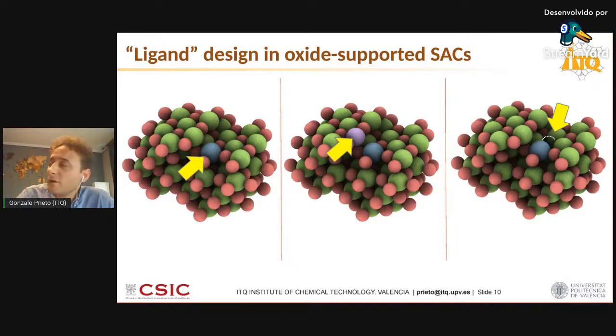Second degree of design relates to the oxide support itself, where we can isomorphically substitute those cations which are intrinsic to the oxide support by different ones. And this way, we are introducing Lewis acid centers close to our atomically dispersed metal with different acid strengths. That's what I represented by substituting one of the green atoms by this purple atom there. Those are cations, and we are changing the Lewis acidity in the neighborhood of our supported metal.